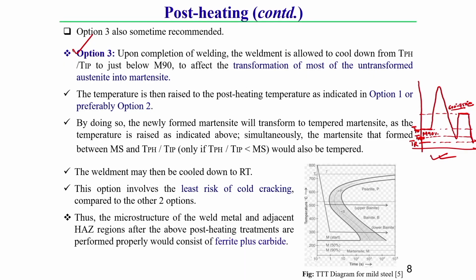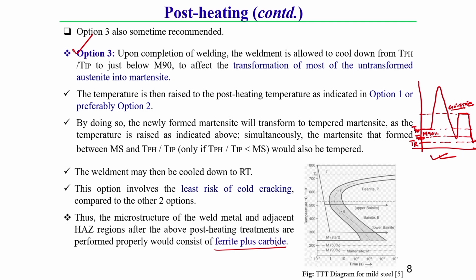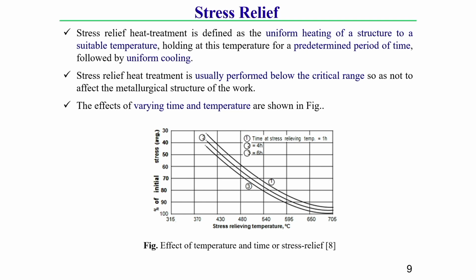So, the overall martensite is then tempered at a temperature of about preheating temperature or 600 to 750 degree centigrade. Both the martensite formed below the martensitic 90% temperature range and the earlier martensite will be tempered, and due to this tempering it is converted to ferrite and carbide structure. So the final structure due to this heat treatment process will be ferrite plus carbide structure.